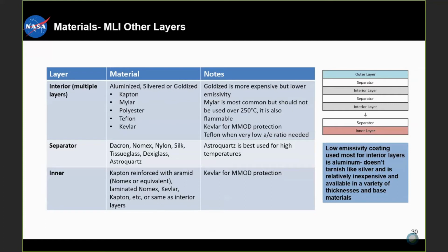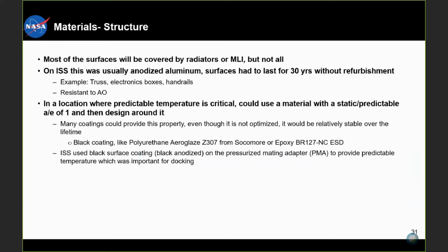In the inner layer, you'll see materials such as Kapton, reinforced with aramid, laminated Nomex, Kevlar, or it could be the same materials as the interior layers. Just a takeaway, the low emissivity coating used most for interior layers is going to be aluminum. It doesn't tarnish like silver, and it also is relatively inexpensive, and it is available in a variety of thicknesses as well as base materials.